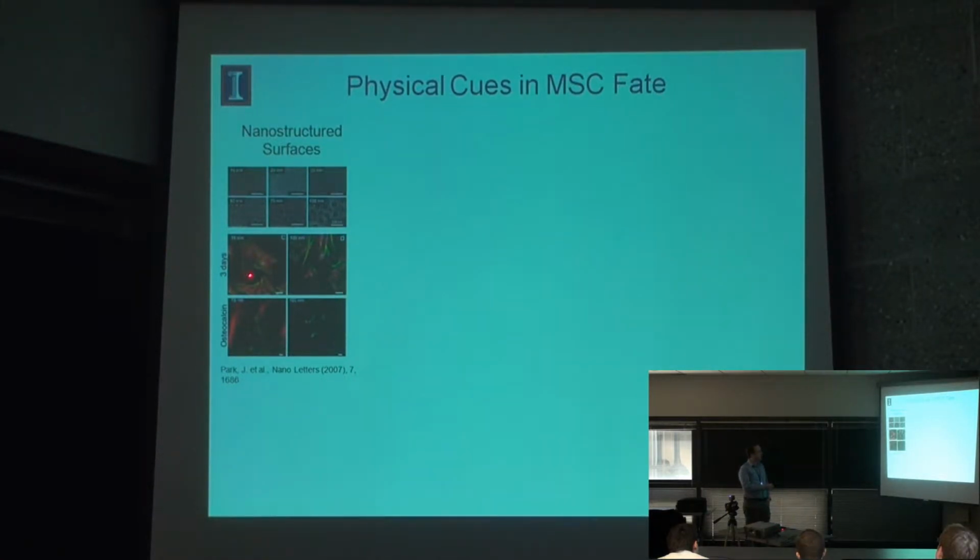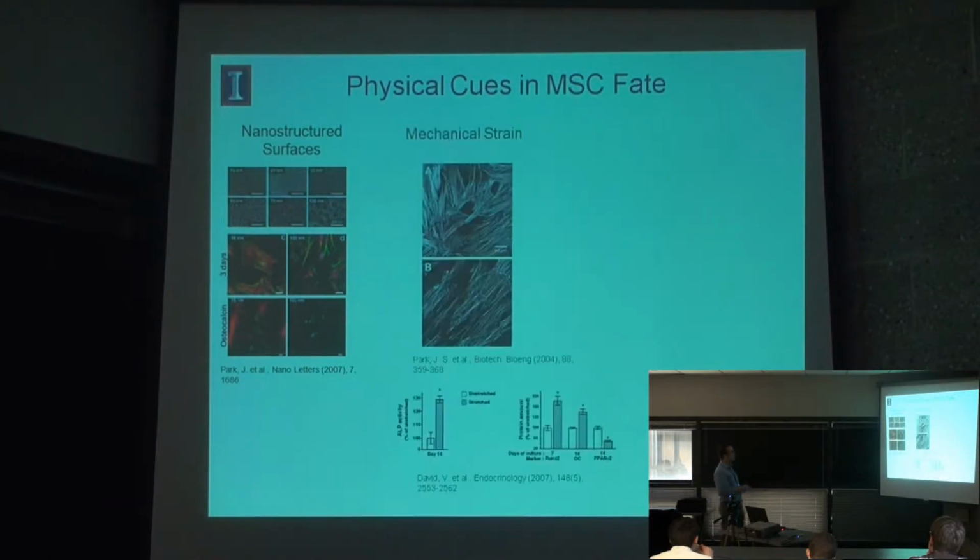they found that cells adherent to these small nanotubes were able to spread out, get a high degree of cytoskeletal tension, and a lot of robust focal adhesion formation throughout the cell, compared to cells that are adherent on these large nanotubes, where they remain rather spindly, and they don't adopt a stable cytoskeletal configuration. And then after several weeks, when they went in and stained for markers associated with bone cell differentiation, they found that cells that were spread out had this healthy, well-developed cytoskeleton, expressed higher levels of differentiation markers for bone.